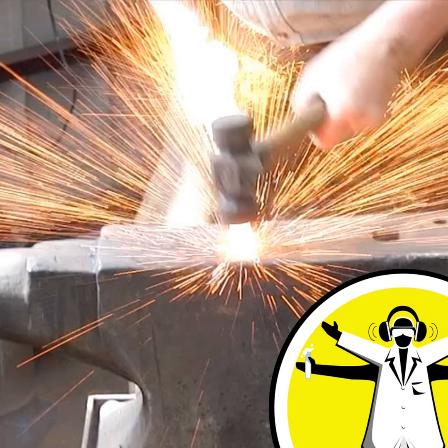We were talking about the metal getting stiffer as we bend it backwards and forwards because of these dislocations locking up. When you heat it up, that gives the metal atoms huge amounts of energy. These dislocations can move past each other, no problem. They actually randomly move around in the metal, and you completely reset the clock and set it back to zero. If you let that cool down slowly, you've got lots of dislocations in there, they're not locked up. So it's really flexible, and you can bend it backwards and forwards until it work hardens again and gets stiff. So that's one effect that we've seen from heating it and then allowing it to cool quite naturally just in the air. But the other one we quenched.